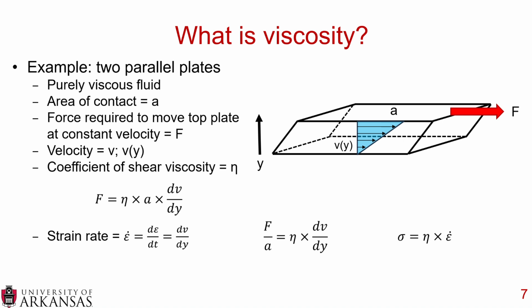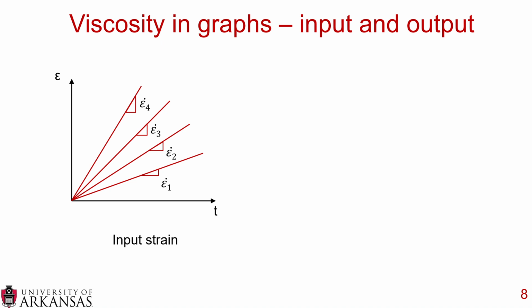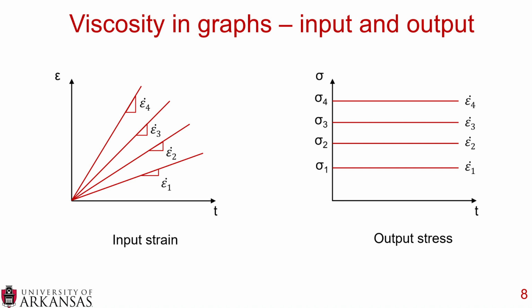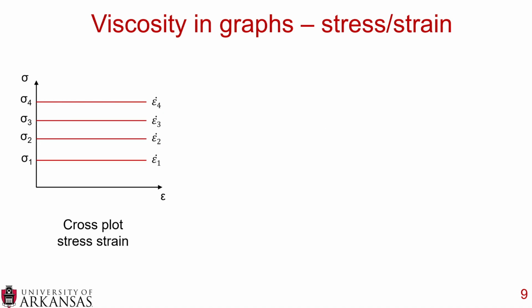Now let's take a look at that in graphical form. Pretend you have 4 different input strains, epsilon 1 through epsilon 4, with strain rates epsilon dot 1 through epsilon dot 4. From those 4 strains, you get 4 different stresses. So you have an input strain and an output stress, and you can cross plot the stress and the strain. Now we have stress on the y-axis and strain on the x-axis, and you can see the 4 levels of stress corresponding to the 4 levels of strain.